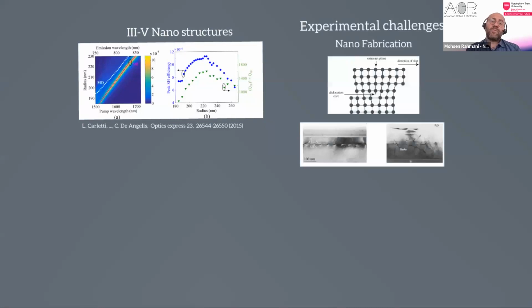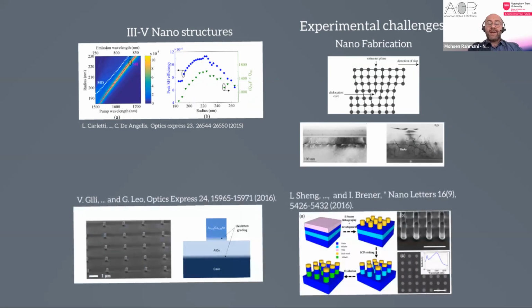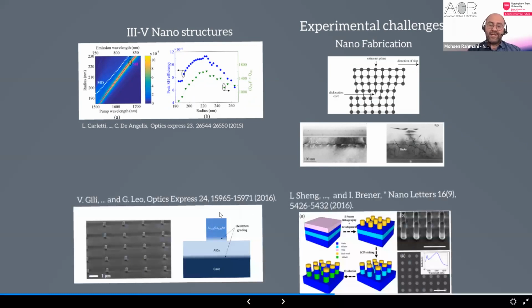So after that, despite the issue that we really could not grow the III-V semiconductor on glass or silicon, and it was a fundamental issue, several groups at the same time tried to solve this issue to generate gallium arsenide nanoparticles, the group of Giuseppe Leo and Igal Brener. So they did it by using some sacrificial layer and oxidizing that sacrificial layer.